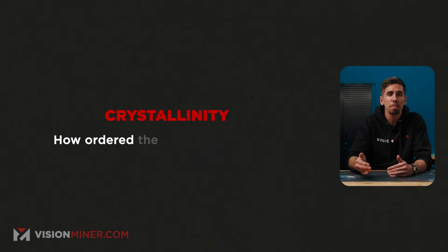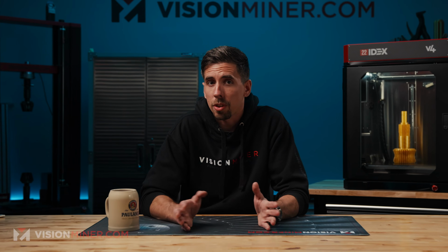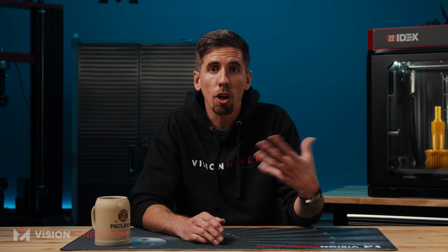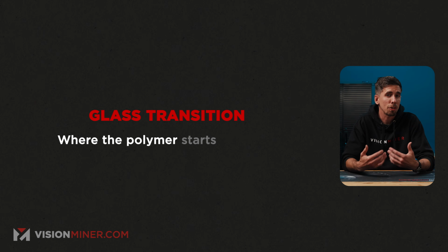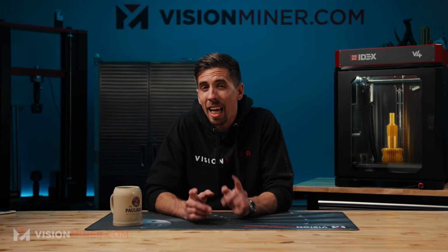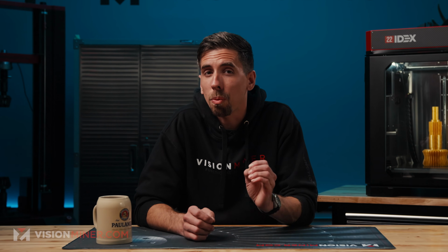So what does that mean? Crystallinity is how ordered the polymer chains are. More crystallinity means stiffer, stronger, harder for chemicals to actually penetrate. Glass transition is where the polymer starts to soften. The material didn't degrade. It actually got a little stiffer and a little more heat resistant. It's almost like the part was annealing itself in service. Imagine if every time you stressed a metal part, it got slightly harder instead of slightly weaker. Now that is the kind of data that gets a part qualified.